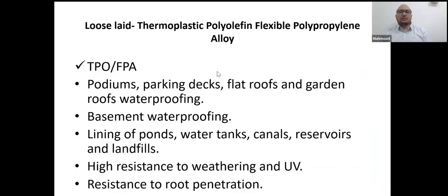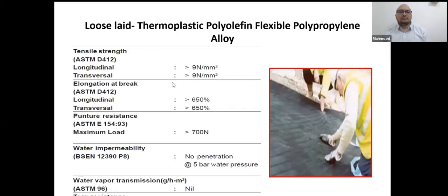The polypropylene modified flexible waterproof membrane is used for podiums, parking decks, flat roofs, gardens, roof waterproofing, and has resistance to UV and high resistance to weathering also. Approved for use in contact with potable water. Elongation is greater than 650. Water permeability: no penetration at 5 bar pressure. Water vapor transmission is nil.